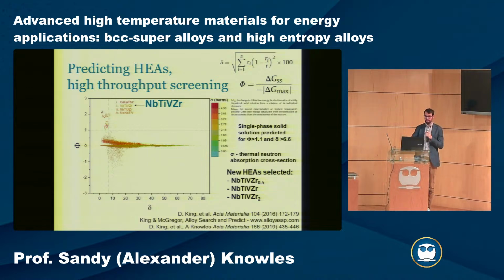Within those 5 compositions, quite a lot of the other ones had uranium in them, and we couldn't handle uranium in our lab, so we didn't do those. We instead looked at this niobium titanium system. And then we could take these different high entropy alloys and do some further study.